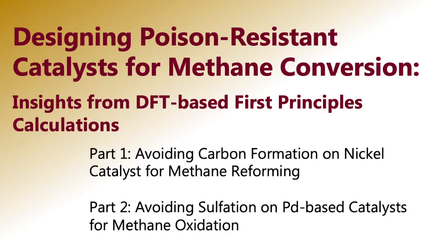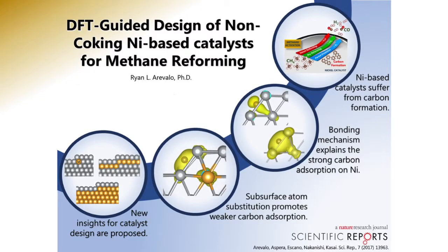In the first presentation, or in the previous video recording, I've talked about the formation of carbon on nickel catalyst for methane reforming. In that presentation, I've talked about our study that was published in Scientific Reports, where we investigated the reason why nickel-based catalysts suffer from carbon formation. So we were able to clarify the bonding mechanism that explains the strong adsorption of atomic carbon on stepped nickel surface, which involves the interaction of atomic carbon with both surface and subsurface layers of stepped nickel surface.